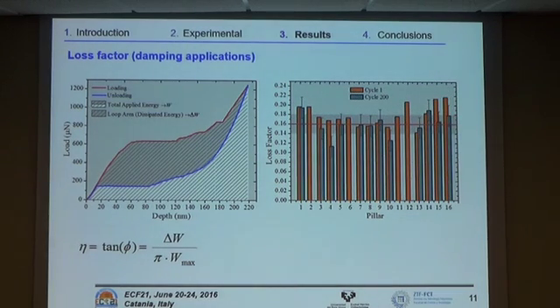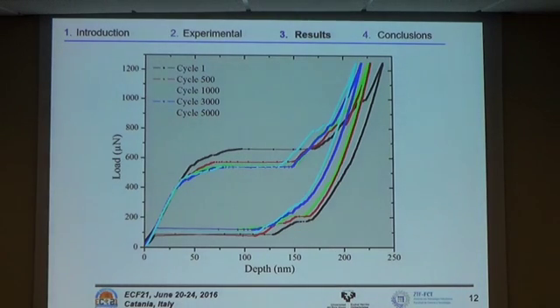If we pass to the 200 cycles, it is observed that on average the damping capacity is maintained, although in some cases, for example pillars 11, 12, 6, due to some stabilization of the martensite, we could not further have the superelastic effect. But anyway, on average, we could say that we have quite good and reproducible damping. But of course, 200 cycles is not too much, so we wanted to go further, and in 4 pillars we were able to go to 5,000 cycles, and as you can see in this image here, again after the initial training, the situation gets stabilized, and we have quite a good damping capacity, or quite a good superelastic cycle after 5,000 cycles.